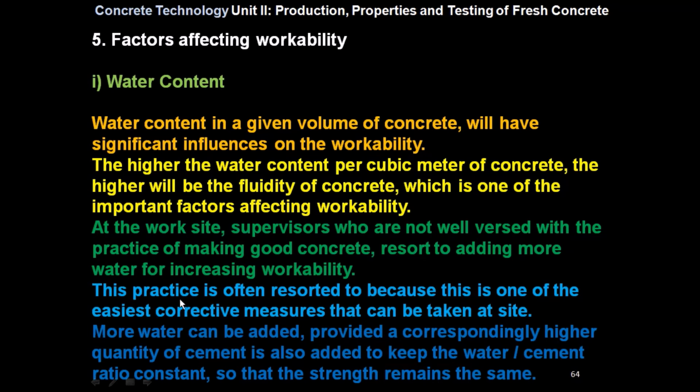This practice is often resorted to because this is one of the easiest corrective measures that can be taken at site. More water can be added provided a correspondingly higher quantity of cement is also added to keep the water cement ratio constant, so that the strength remains the same.